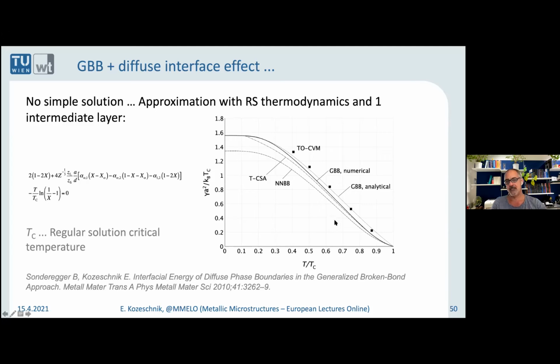And what you can see here in this graph is that there's also some kind of a factor which decreases the energy. Let's say if you start at the unit value here, then with increasing temperature, the driving force goes down, and it goes to 0 once you reach the regular solution critical temperature. And the comparison with other approaches published in literature has given us very nice confidence that the approximate solution is not too bad. And we are using that on a regular basis now.